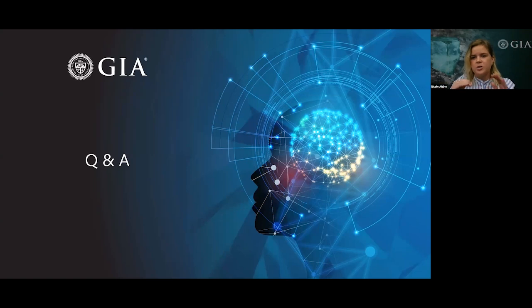And so you saw that because it was well-formed crystal. As that corundum was growing, that titanium oxide was present in an equilibrium to create a rutile crystal and not corundum in that space. So as that corundum was growing, that rutile was growing as well as a syngenetic crystal. And then you can see exsolution rutile silk, which is more of an epigenetic.